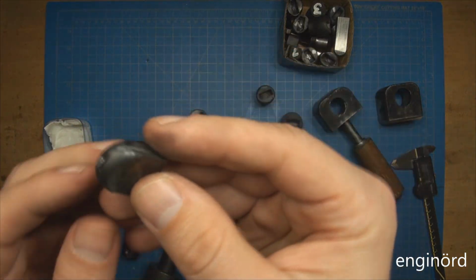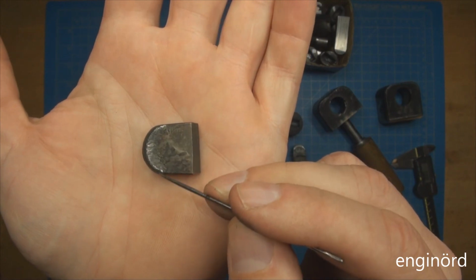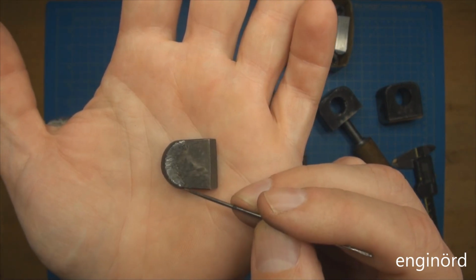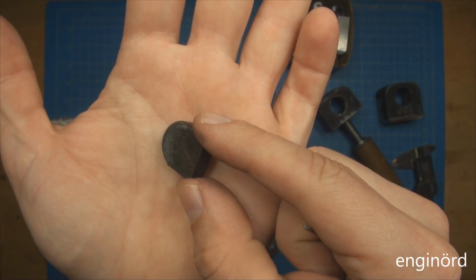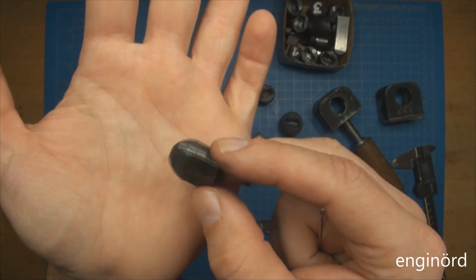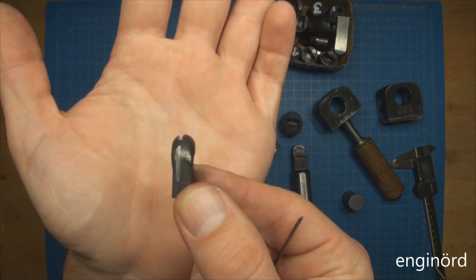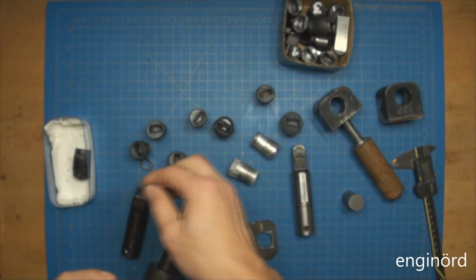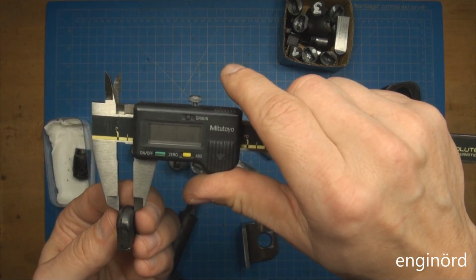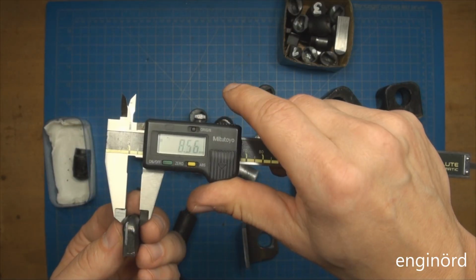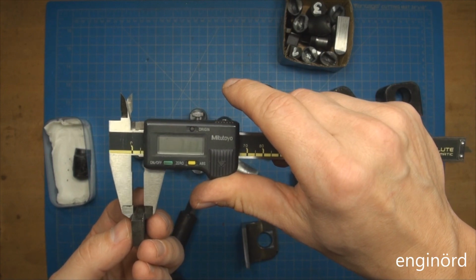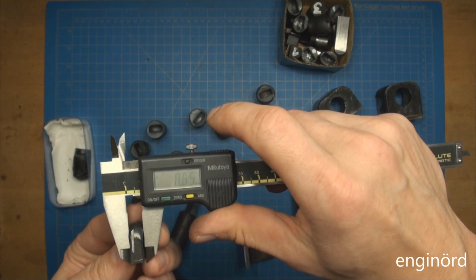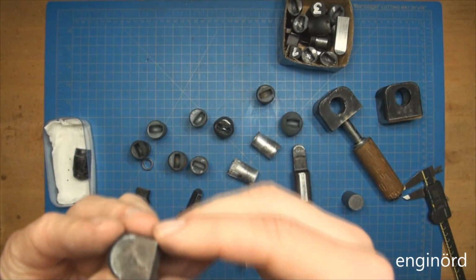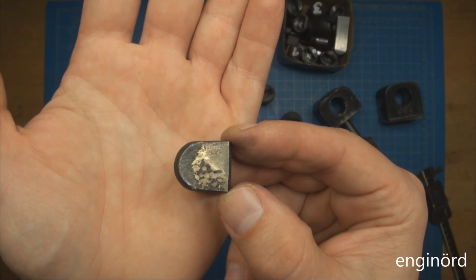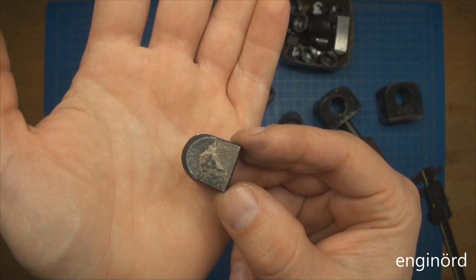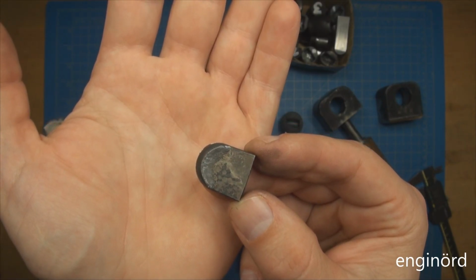So even in this case, you can see that a portion of the workpiece got hot welded to the tool itself, so that when the tool was retracting, it was making that cavity bigger. So here you can see on the side view that it's much wider than it's supposed to be. The tip of the tool should be around 6 millimeters. This is 8.5. And then here in this back section it should be around, you can see it's around 7, and then the tip is about 8.6. So clearly there was material transfer from the workpiece to the tool, which is not good, especially if I just use it one time.